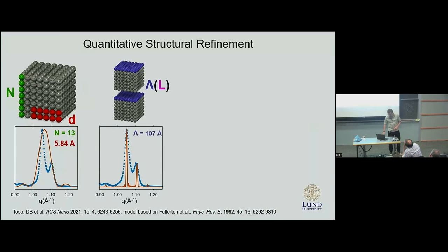Then we can add a parameter of superlattice periodicity, which would perform a convolution of these superlattice peaks with a broad peak, producing something that doesn't look anything like the experiment shown in blue, because it's way too perfect.